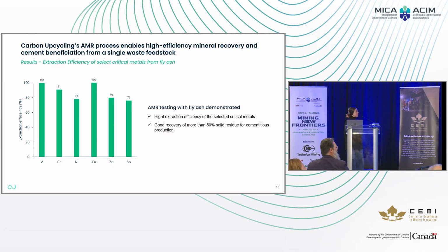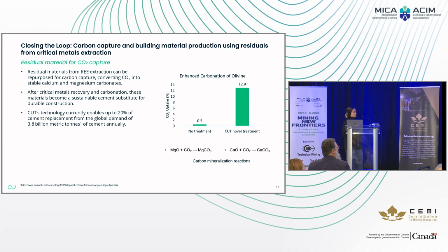as SCM. So to close the loop, the residue recovered in this process is then used for CO2 capture. We capture the CO2 from the atmosphere in the form of a stable magnesium carbonate or calcium carbonate. So we have more than 20% of cement replacement in this case, and we can reduce the global demand of cement annually in the world.